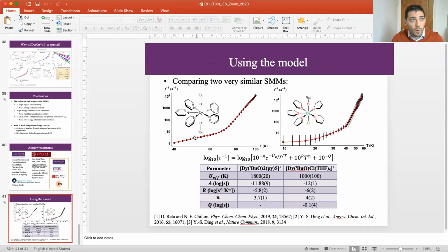As far as I'm aware, there is no good correlation that's been done yet on the effective G tensor. The effective G tensor for the Kramers doublet reports on the mixings of the different MJ projections into the ground state. So if you have a pure plus or minus 15 over 2, you should have 20, 0, 0. When you don't have a pure state, which in reality you never really will, you have 19 point something something and 0 point something something. And so the order of magnitude of those is very important, as you say. But I don't believe anyone's made a study on the correlation between those effective G tensor values, specifically the transverse.